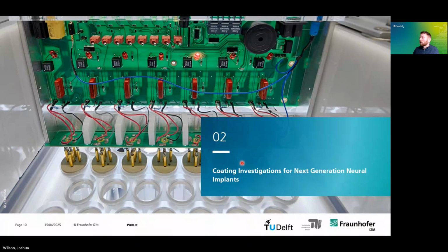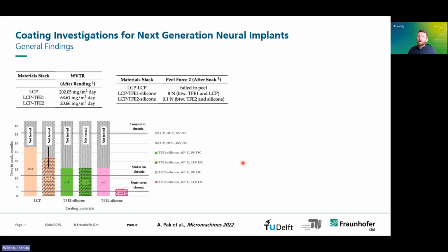Okay, so coating investigations. First, I will start with some general learnings. Don't get bogged down on the specific materials at the moment. I will clarify when the materials become important. So when you want to put an electronic system inside a human in a very wet environment, you would imagine that a good thing to have to protect your electronics would be a water barrier. And so we have here in the table on the left-hand side a set of material stacks. These are polymeric materials, and we measured the water vapor transmission rate through these. So the amount of water that is passing through these thin materials over time. And what we see is as we go down the table, the amount of water that passes through is reduced.